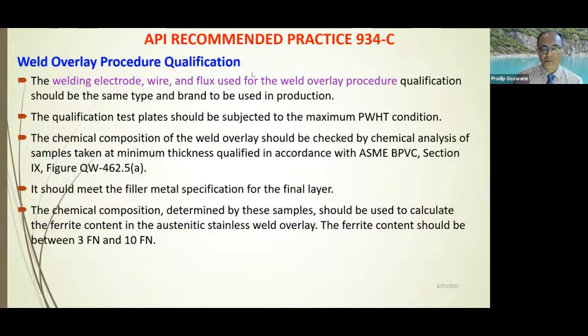And what do we do during the weld overlay procedure qualification? The weld electrode and flux used for weld overlay procedure qualification should be the same type and brand to be used in the production. So basically the same type, brand, and preferably the same batch also, if one wants to be too restrictive. The qualification test shall be subjected to a maximum post-weld heat treatment condition. The chemical composition shall be checked at the minimum thickness, that is typically the qualifying thickness, as specified by the requirement as per Section 9 as well as the project specification.